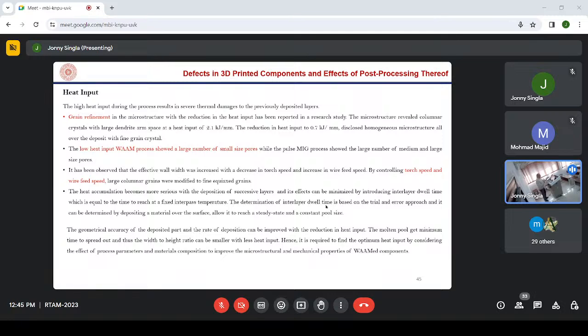Heat accumulation becomes more serious with the deposition of successive layers, and the effects can be minimized by introducing, this is very important, interlayer dwell time, which is equal to the time to reach a fixed interpass temperature. You make one layer, then you give a pause for a certain time.